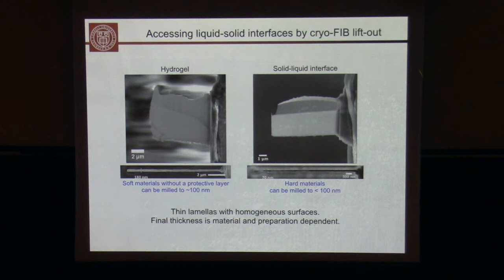Here are two examples. This is a hydrogel with nanoparticles incorporated or grown in the hydrogel. Turns out when you grow nanoparticles in hydrogels, the surface structure or crystalline structure can be quite different. Just as an example, if they are soft like hydrogels, usually the samples are thicker, maybe on the order of 100 nanometers. If you have a hard material, this is our integrated field effect transistor, that's the liquid, that's the oxide, you can get down way below 100 nanometers. Okay, so this is just sample preparation. In fact, that was the bottleneck of why nobody could image these liquid-solid interfaces at high resolution.